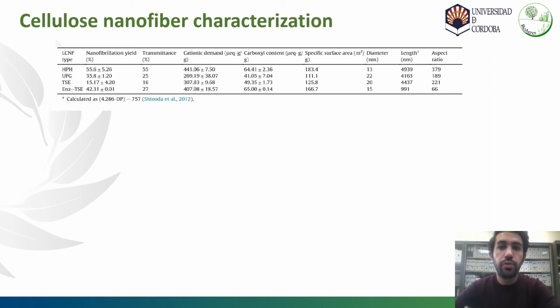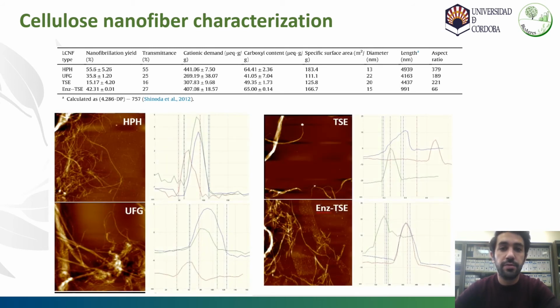Four different types of lignocellulose nanofibers were obtained: high-pressure homogenization, ultrafine grinder, and extruder, and the one from the extruder but with enzymatic pretreatment. Of these lignocellulose nanofibers obtained by mechanical treatment, it is known that those obtained by homogenization are the ones that present the best result in yield. However, all of them present very acceptable diameter values that were verified using AFM.